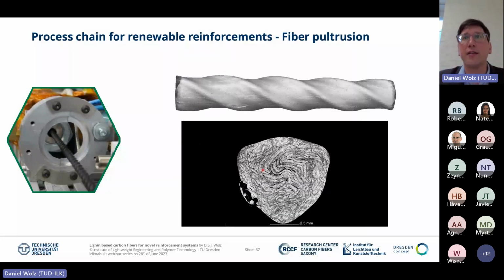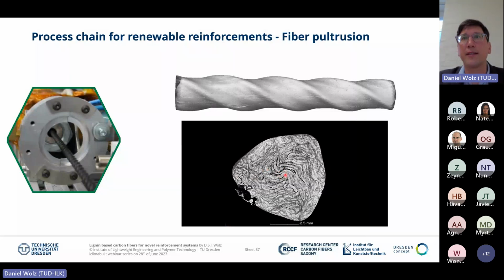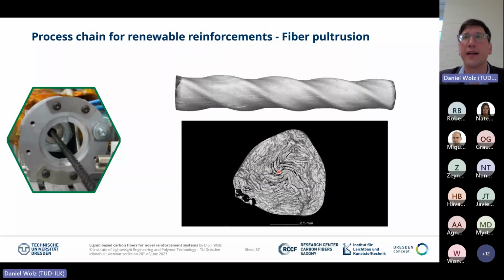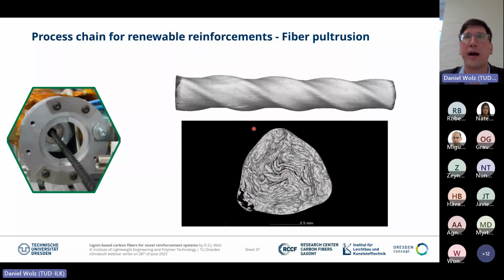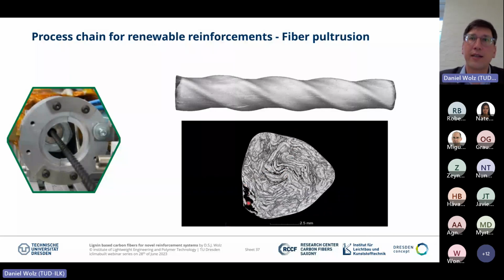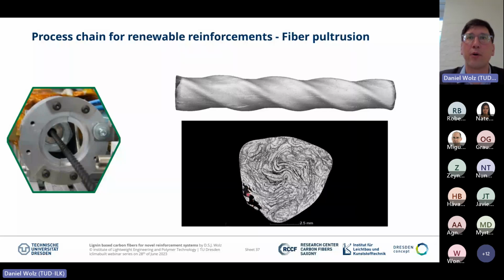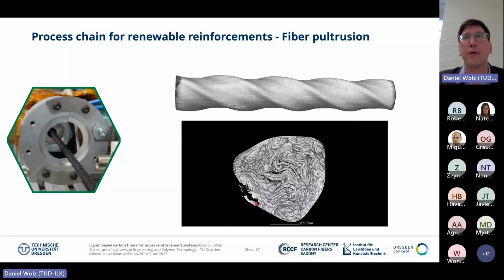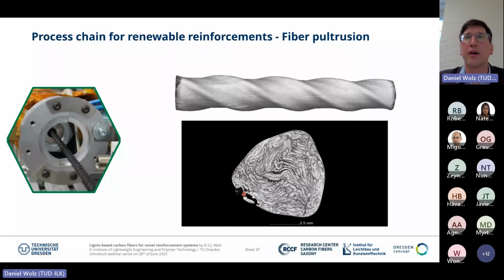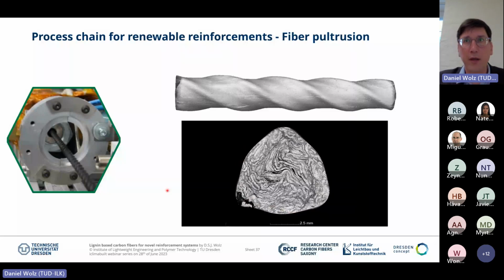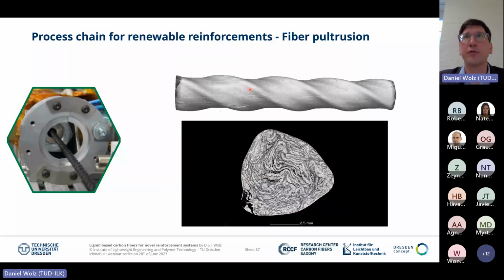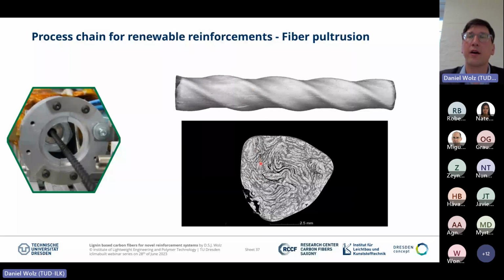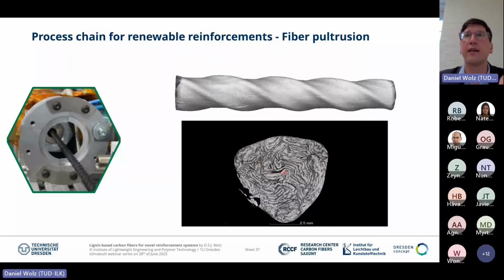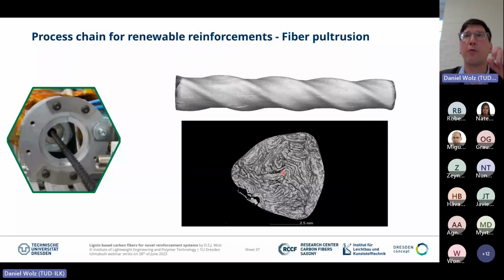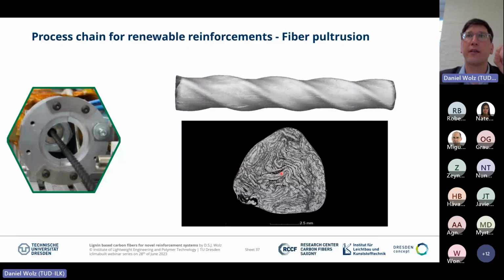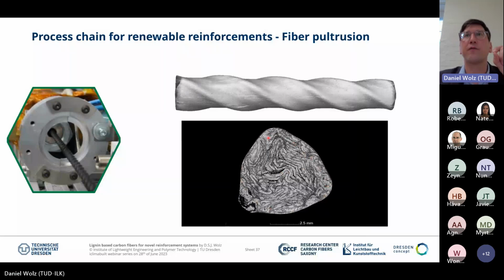tomography. You can see that the neutral fiber line is still located at the same position, even if the outer fibers are changing. This little smooth point is a polymer-rich region, which you do not see in the computer tomography analysis. So with this pultrusion by the nozzle, we can build a carbon fiber rod where the neutral line always keeps the load-bearing function in the same direction, while the outer points are diverting.